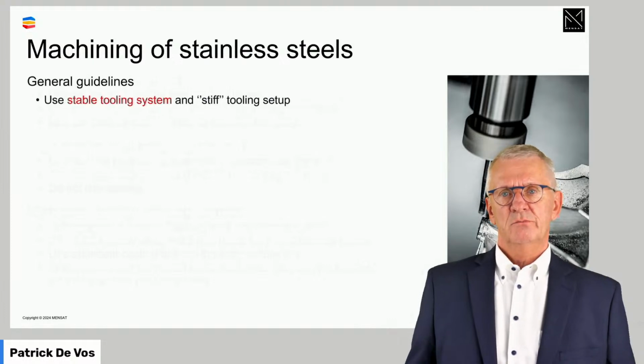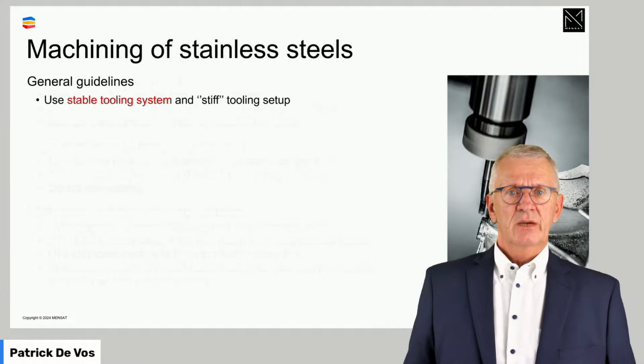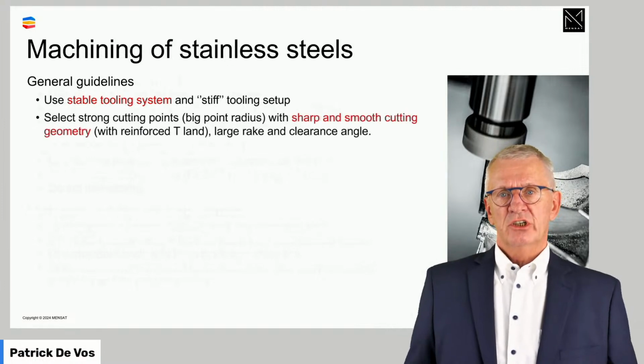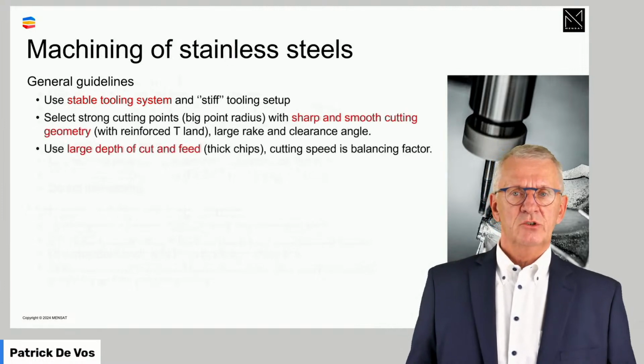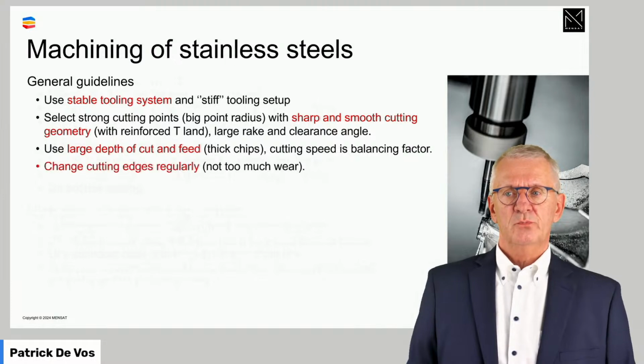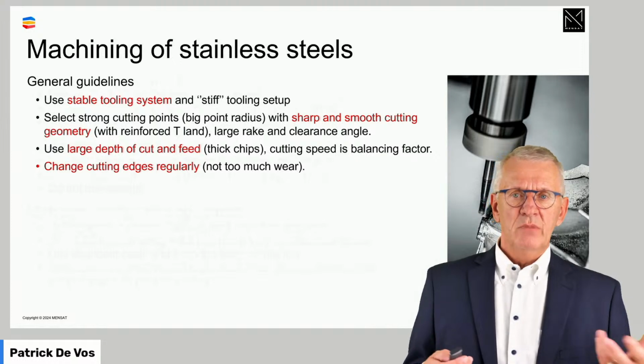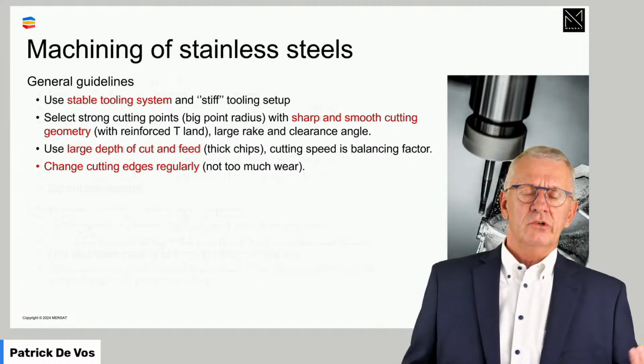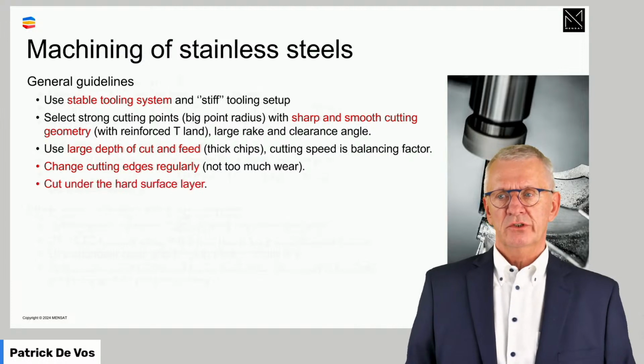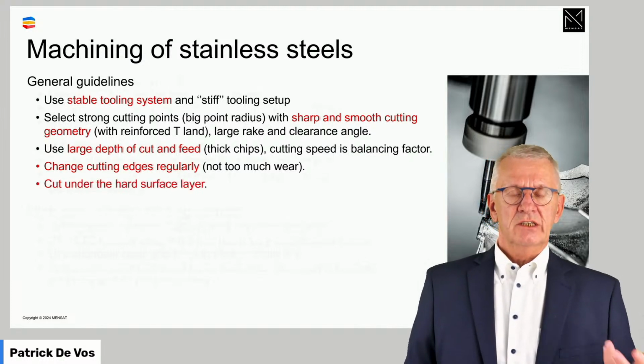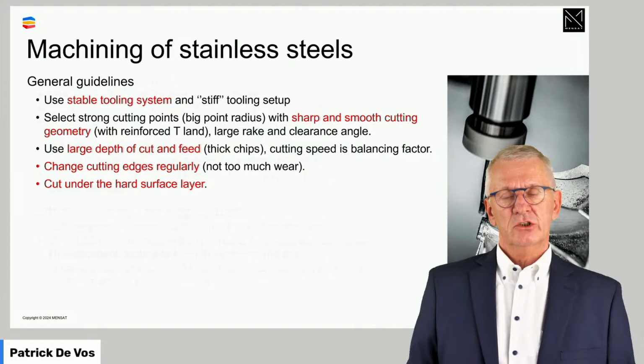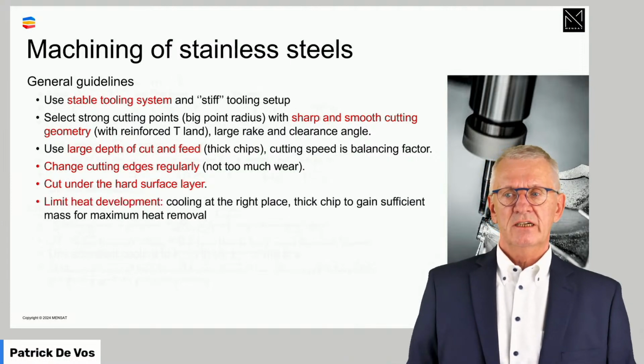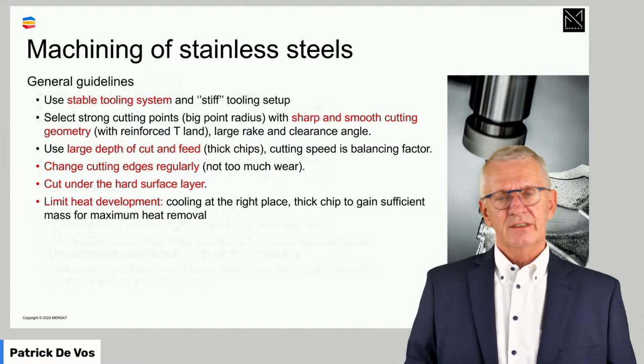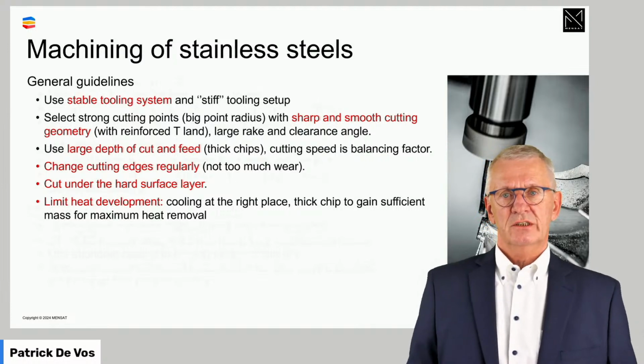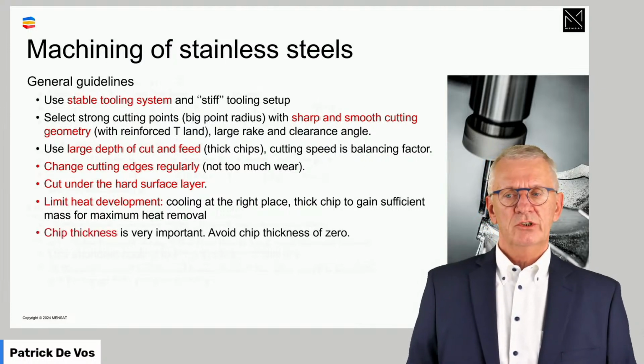General guidelines: if you machine stainless steels, stable tooling, sharp geometries, large depths of cut and feed. It's all based on experience. Change cutting edges regularly. Remember that you will use more cutting edges. Tool life will be shorter. Think on it that stainless steels have hard surface layers, chromium oxide, strain-hardened layers. Think on heat development. It's limited, because you could end up in critical temperature things.